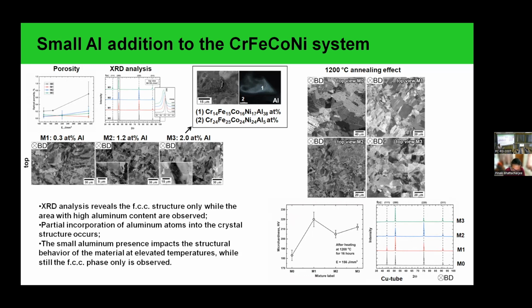But we didn't make a TEM observation of this phase, so we don't have the TEM diffraction analysis to say this is exactly the B2 phase. Okay. So basically you are not sure whether it is a disordered BCC phase or an ordered B2 phase, right? We assume that it is an ordered B2 BCC phase, but for a strict conclusion, we need the TEM observation, which we have not presented.